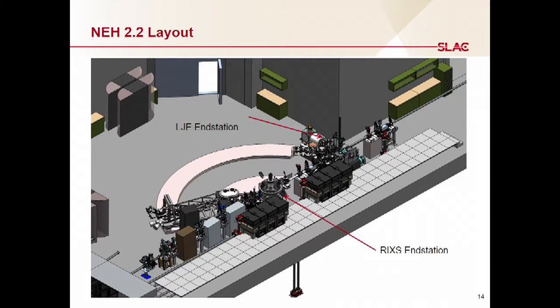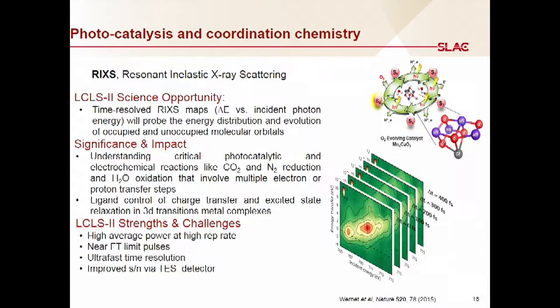Keep in mind, this RIXS technique is very, very photon hungry. So you measure one photon out of 100 million or so that you put on your sample. So it's really time consuming. And we hope to really change the game with LCLS-II when we have much higher flux. And we also want to have a second end station, which will be located somewhere downstream, that can essentially do the same technique but on liquid samples. And I'll tell you a little bit more about that in a second.